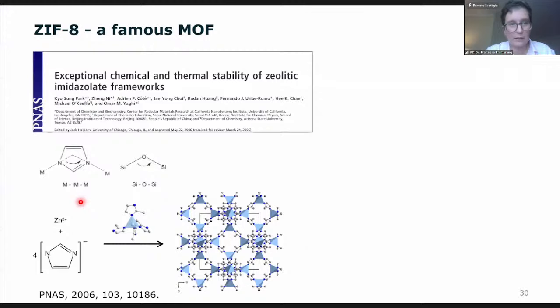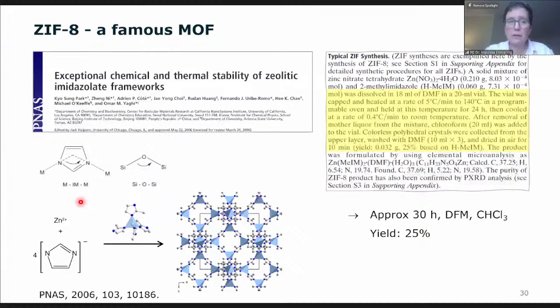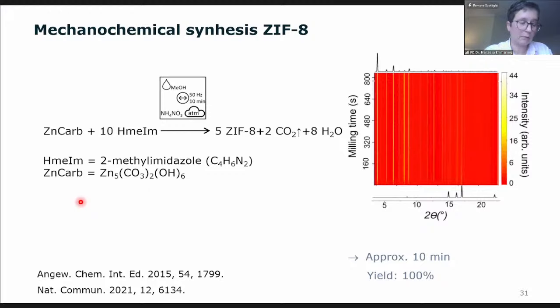And here you see the original article by Yaghi and colleagues. And you can see that's a normal reaction time, around about 30 hours. They use DMF and the yield was about 25%. We and other colleagues also looked into the mechanochemical process forming this ZIF-8 compound. And you can see here that can be done much faster. So within 10 minutes, you have a conversion and 100% yield.